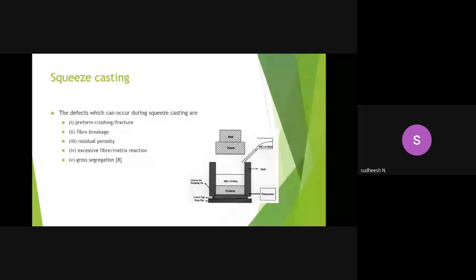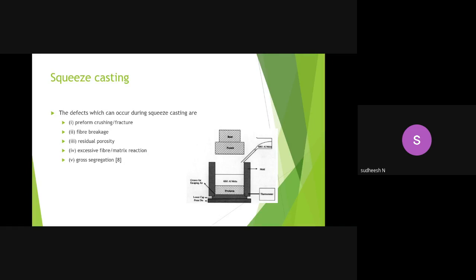The major defects which can occur during squeeze casting are a chance of fracture or breakage in the fiber we are adding as a reinforcement, and it may have porosity. There is a high chance of creating porosity on the surface of the metal composite, and gross segregation may also occur due to the high pressure acting on top of the metal matrix.